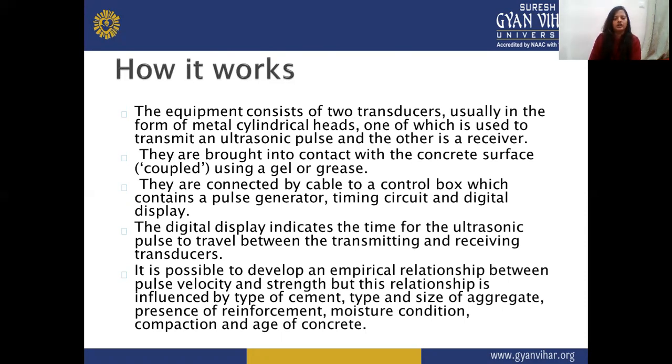It is possible to develop an empirical relationship between pulse velocity and strength, but this relationship is influenced by type of cement, size and type of aggregates, presence of reinforcement, moisture condition and compaction, and the age of concrete.